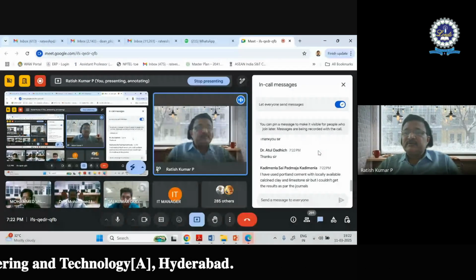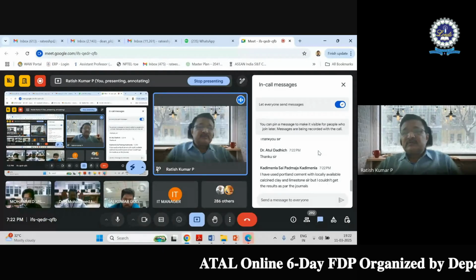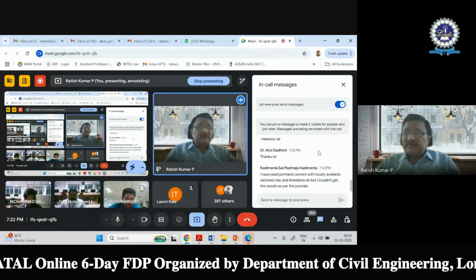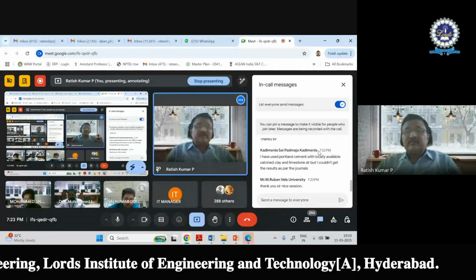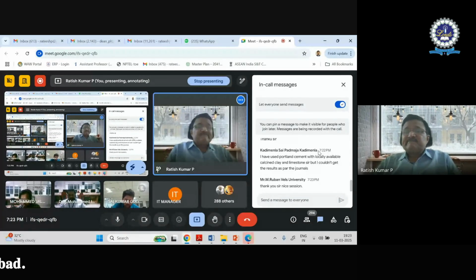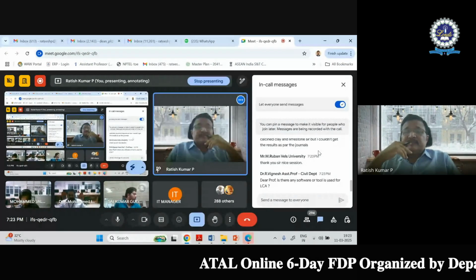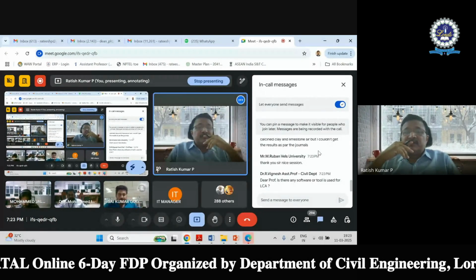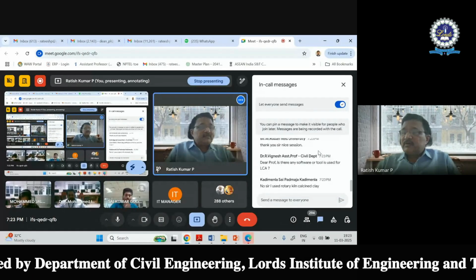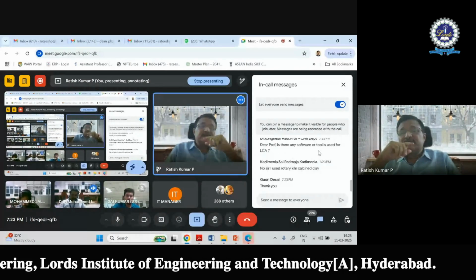I've used Portland cement with locally available calcined clay and limestone, sir, but I couldn't get the results. You can try with geopolymer, but how much Portland cement have you used with the available calcined clay? So you have calcined the clay by burning it in a muffle furnace at 800 to 900 degrees centigrade and got the calcined clay. Limestone calcined clay should give results, and you can also try it in geopolymer. In fact, that's another research area we can think about.